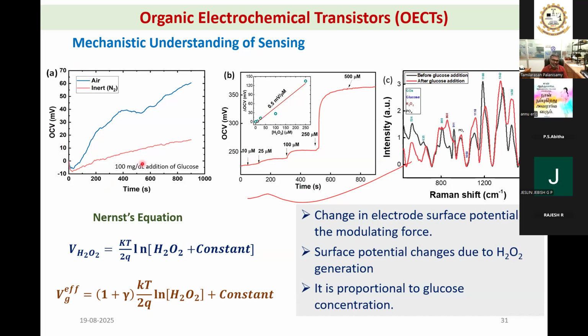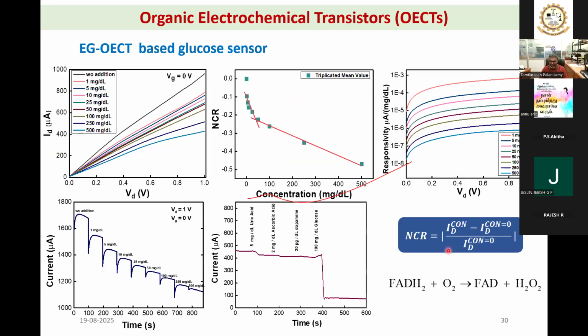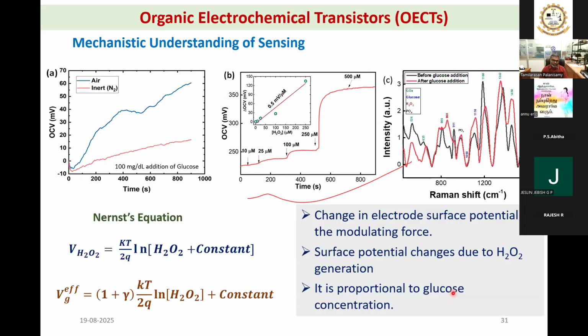On the other hand, we also should prove that this H2O2 is coming from the glucose oxidation. That is one important thing. If you remember the reaction, the reduced form of FAD is regenerated back only when it is reacting with oxygen. So in case I restrict that oxygen, what will happen? That's what the study here is. If I do the experiment in an inert atmosphere, my OCV generation is very minimal.